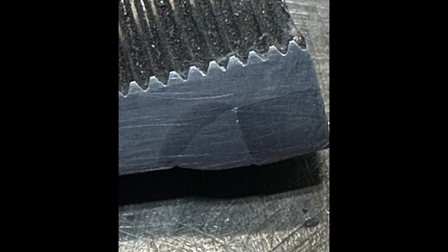And this is kind of interesting because I expected it to be a bit better than this. But again, the settings are a bit on the cold side simply because we have more metal here than you would normally have just doing, say, a lap weld on 3/16 thick material. So now let's look at a little bit of a bump in settings and see how that looks.